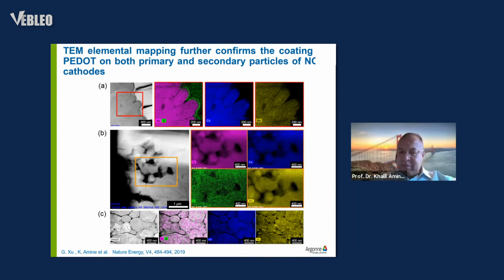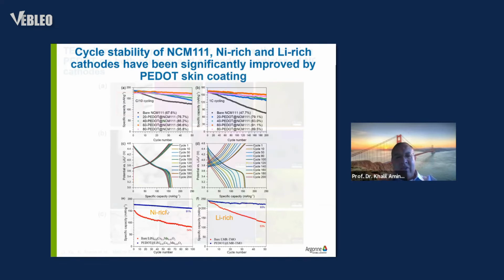So the impact of this protection is a significant improvement in cycle life. This is a nickel-rich material. When you have nickel-rich, the reactivity is high. So when you operate at high voltage and high temperature, you can see the capacity fade without protection. With protection, you get much better stability. At high voltage, 4.6 volt, we get about 250 milliampere-hours per gram. And you can see clearly that the protected material shows very sustainable cyclability, while the non-protected material goes down very quickly.